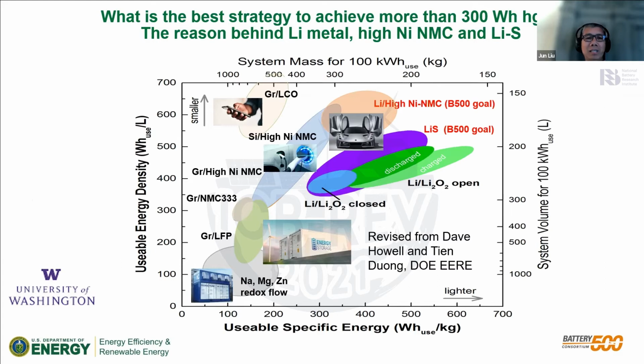As I said, the commercial lithium cells are graphite and either NMC or lithium cobalt oxide. And graphite, lithium iron phosphate, they don't have the highest energy density, but they are very stable. Therefore, they are widely used for energy storage today. Now, the graphite lithium cobalt oxide is the one we use in our cell phone, and the high nickel NMC system or high capacity lithium cobalt oxide or NCA system are the ones we are using for electric vehicle.